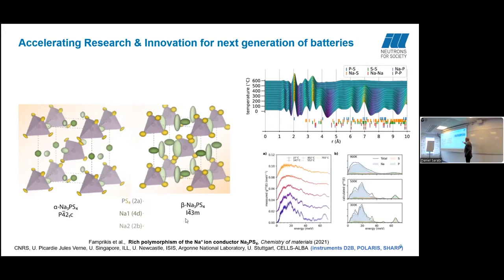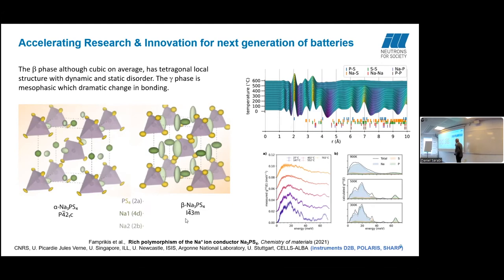And that's confirmed with inelastic neutron and density of states measurements, which show that above 500, there are no local vibrations in sodium, it's just a fluid. So this study showed that the beta phase, although it's cubic on average, has tetragonal local structure with dynamic and static disorder. Gamma phase is mesophasic, and there's a complete change.